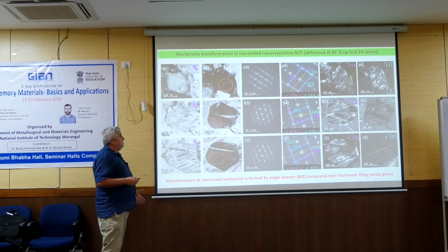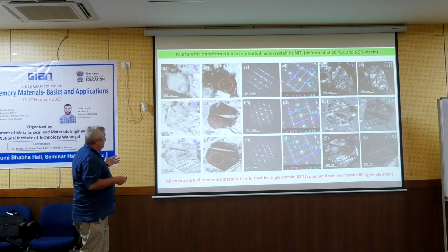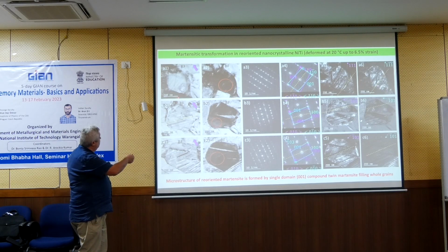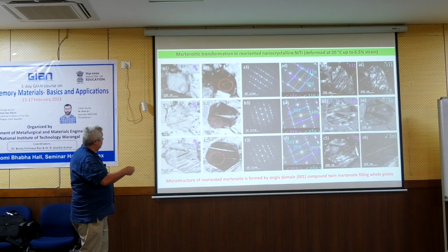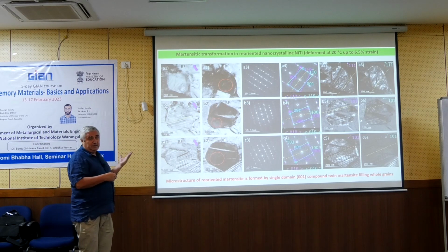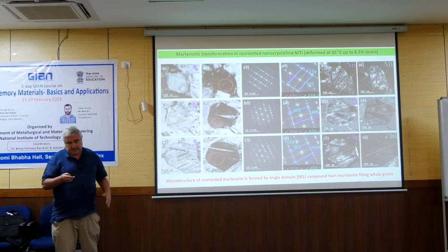And the important point is that we really analyzed something like 20 grains. I'm showing here only 3, but in all 3 cases, the whole grain is filled by 001 compound twins.